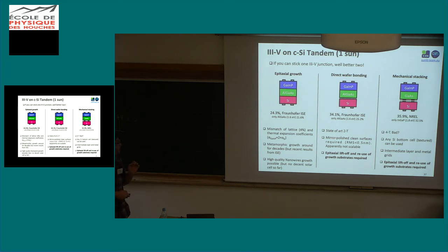The big deal here is that you really have to take care of the interfaces that you are going to bond. They have to be perfectly flat, no dust whatsoever, and it looks like this process is not really scalable. And of course, you still have to grow this III-V solar cell, remove it from the substrate, and possibly reuse your III-V substrate again and again and again to lower the price a little bit. So this is the problem here.